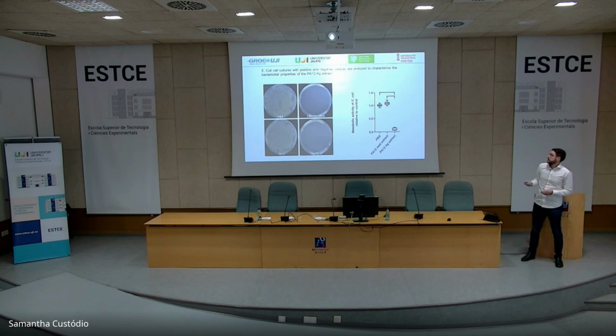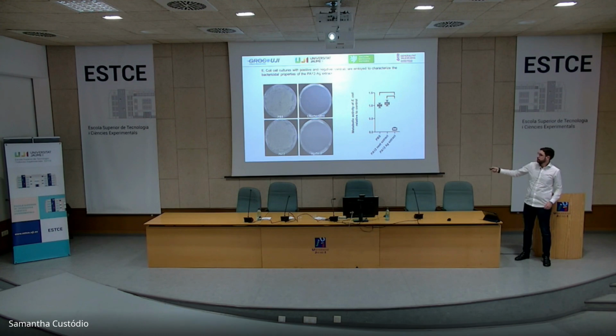So here you have the preliminary, initial test that we did. Here you have the control. So we have the PBS where the bacteria were growing quite well. We have the chlorhexidine where all the bacteria, there was no growth there, so there was inhibition of growth. And here we have the two samples of the liquid after we immersed the base material, the nylon part. And here, what we immersed was the PA12 part with the silver. And you clearly see the difference.